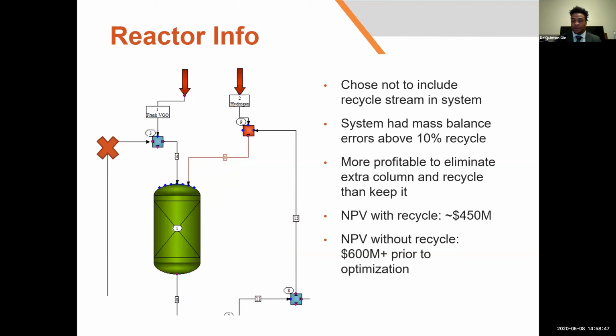And then, reactor info. I'm sure many people wondered why we didn't recycle our unconverted VGO, even though we were making so much money on resid. The system had mass balance errors above a 10% recycle due to the complexity of the kinetics as you increase recycle. So every 10,000 or 100,000 pounds of VGO that we recycled, the kinetics had to be tweaked further, had to be more precise, had to be readjusted. And it got to the point where it was more economical to not recycle any of it and to just let it be sold as resid. So as you can see, our NPV with the recycle was around the $450 million mark. But when we took it out and decided to sell it as resid, we got 600 million plus before optimization.